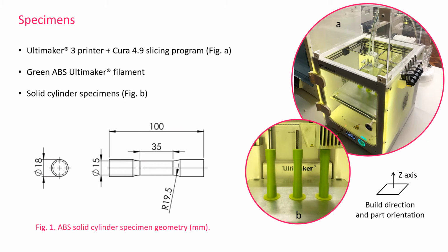Methodology. ABS from Ultimaker in the form of a green filament was selected and solid cylinder specimens were printed using Ultimaker 3 and its own slicing program Cura 4.9, shown in Figure A. Since there is no specific standard concerning the additive manufacturing of polymeric cylindrical components under monotonic torsion and cyclic loadings, the guidelines from the ASTM E143 and ISO 18338-2015 were taken into consideration to design the test method and specimen shown in Figure 1.